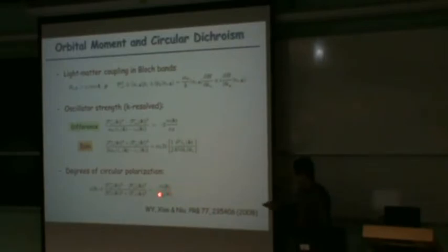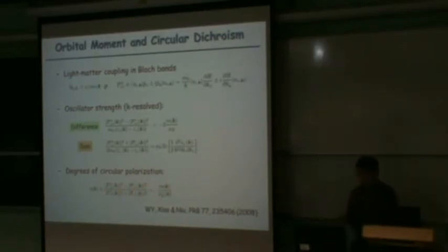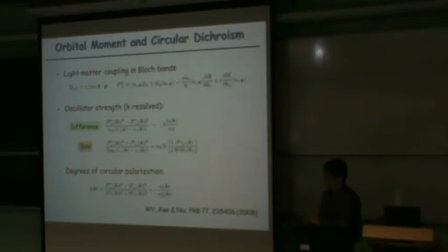And here is the effective Bohr magneton. You can see from the calculations, the values at K and K prime are just the same but with opposite sign of orbital moment. So from this model, you can see at K values, the optical transition possibly corresponds to the left-handed circular polarization, and K prime corresponds to the right-handed circular polarization. That's a direct result of the inversion symmetry breaking in biased bilayer graphene.